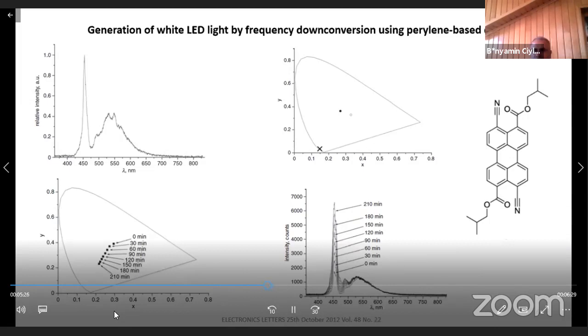During the LED's working time, the optical transmission of the coating tends to increase. The two graphs at the bottom were obtained under stress test. As can be seen, color shift was observed and color rendering index is generally low in down conversion, and an extra layer may be required to prevent dye degradation during LED's operation.